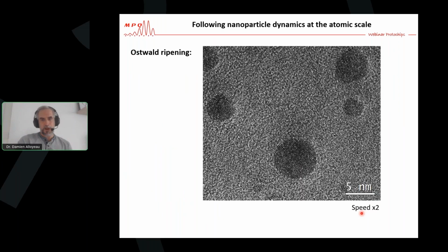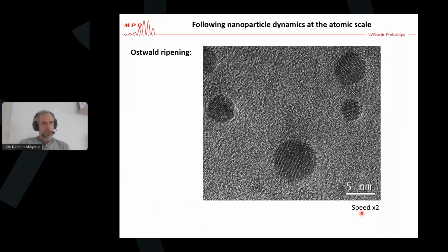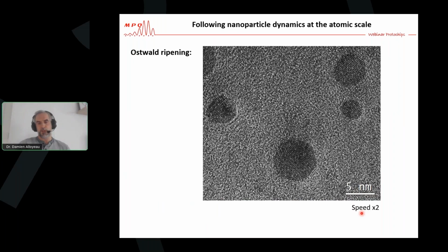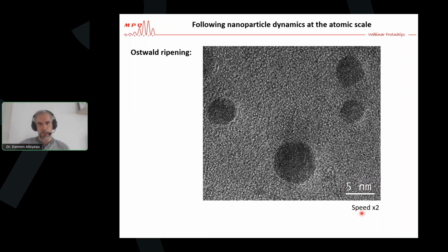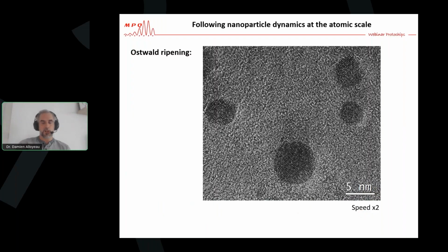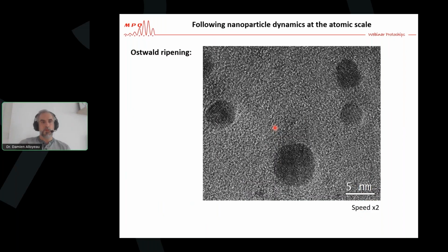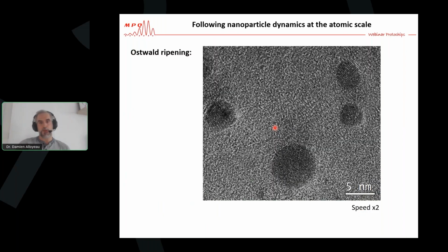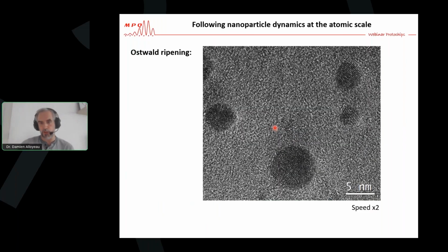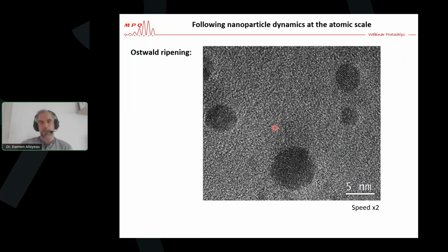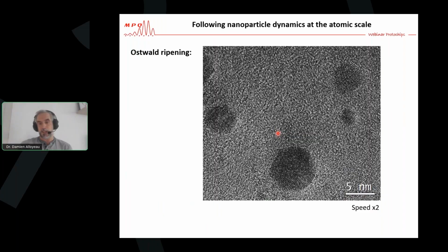Now, those nanoparticles, as I told you, most of the precursors have been reduced, so they are inside the nanostructures. So they keep growing, but now they grow by Ostwald ripening. And Ostwald ripening consists in the growth of the biggest nanoparticles at the expense of the small ones. And that's what you see here.